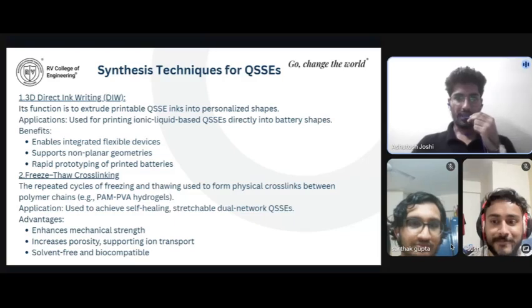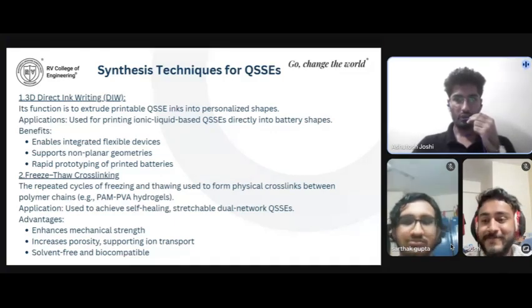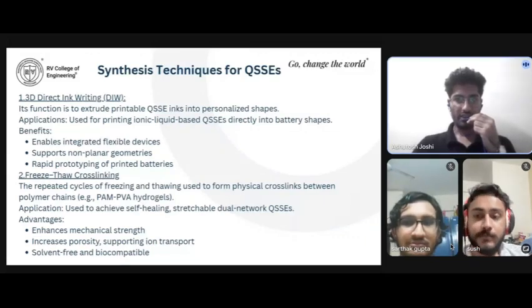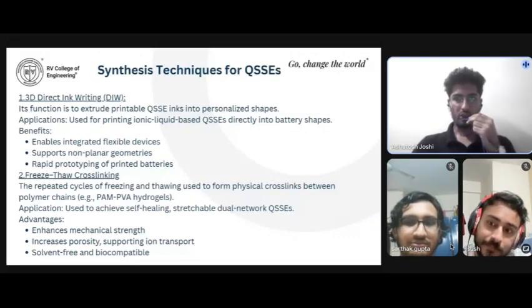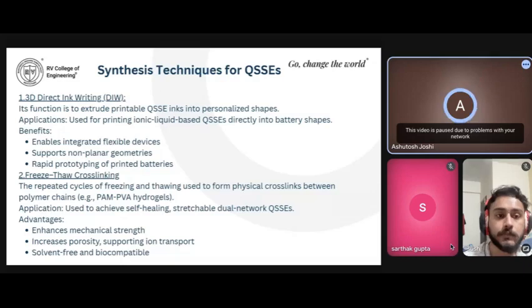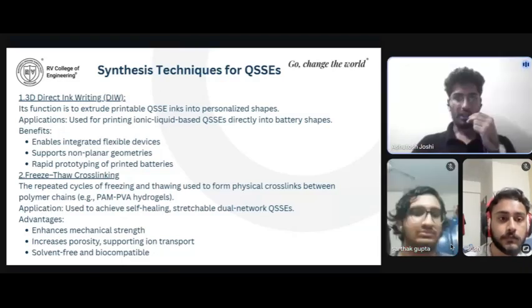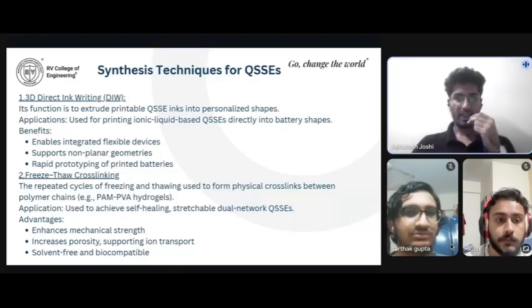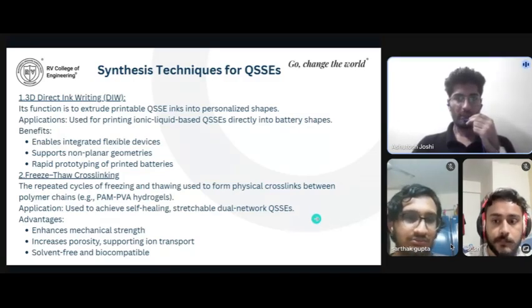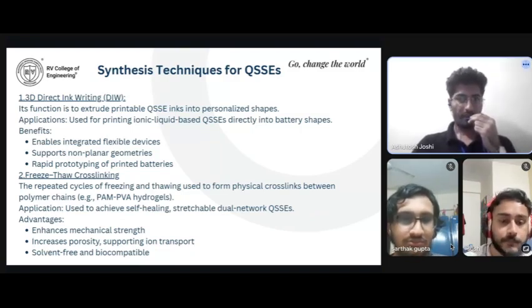Next, its mechanism involves subjecting the polymer solution to repeated freezing and thawing cycles. During freezing, ice crystals push the polymer chains close together, and upon thawing, physical hydrogen bonds or crystallites are formed between chains, creating physical cross-linking. Its application includes creating dual network QSSEs that are self-healing, stretchable, and have high mechanical integrity. Its advantages include no chemical cross-linking requirements, creating highly porous structures, and greatly enhancing mechanical toughness. Next slide.